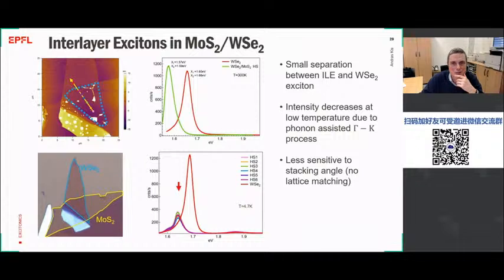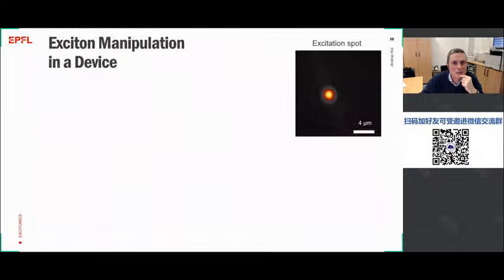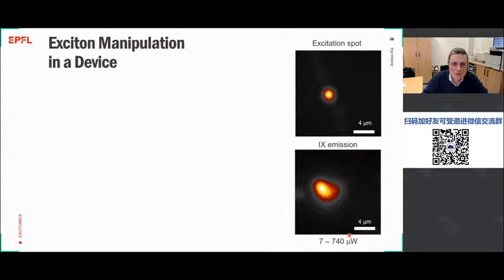Now, once we have these excitons in the materials, how can we manipulate them electrically, and how do you know that the excitons are moving and doing something? So the easiest experiment that you can do is that you can just shine a laser light onto your heterostructure, and you can record the shape of the excitation spot under a microscope and a camera. And then you can easily see that as you change the power of the excitation, this spot is going to change in diameter. And this is what's happening here, for example.